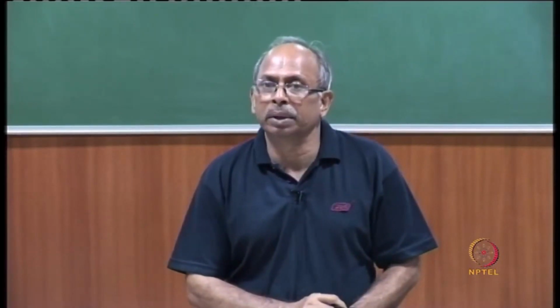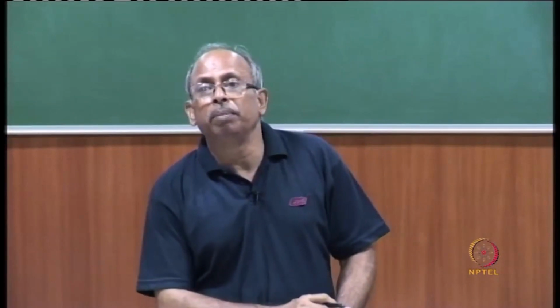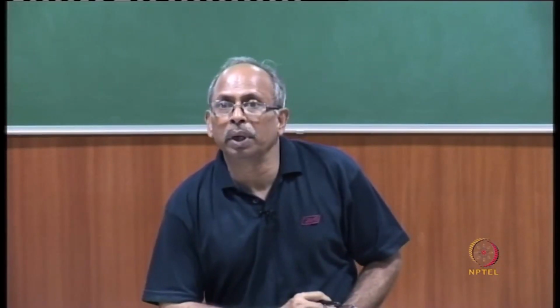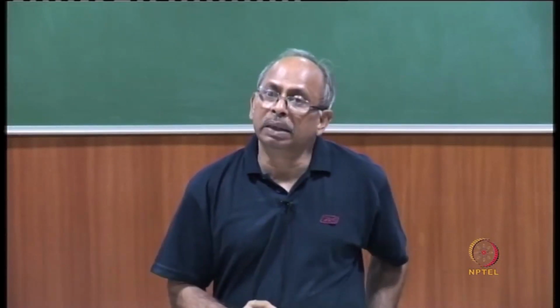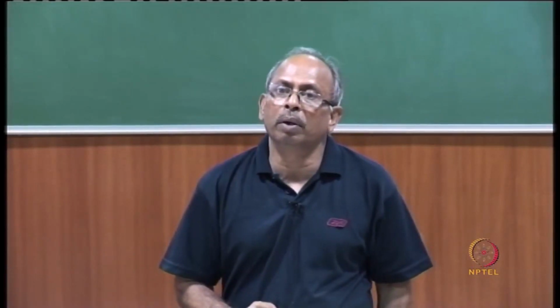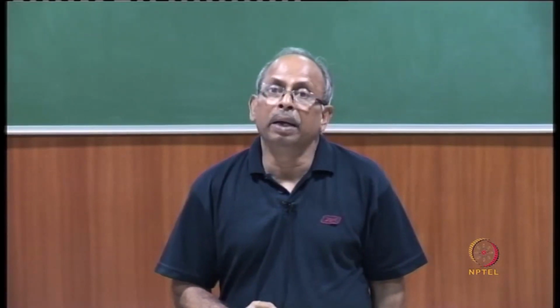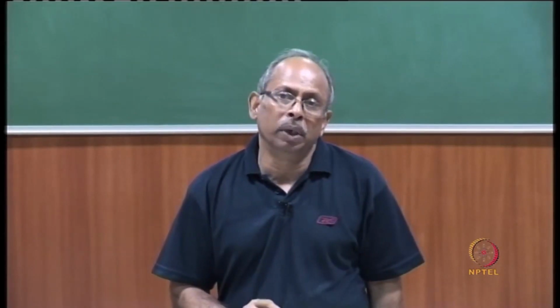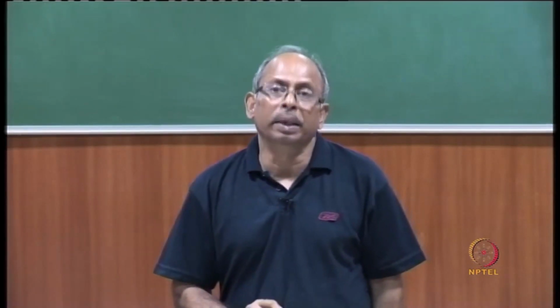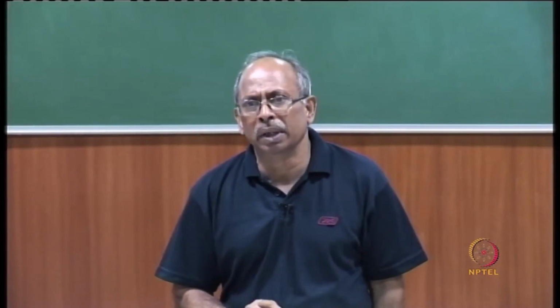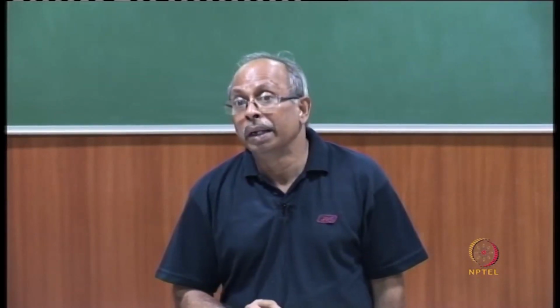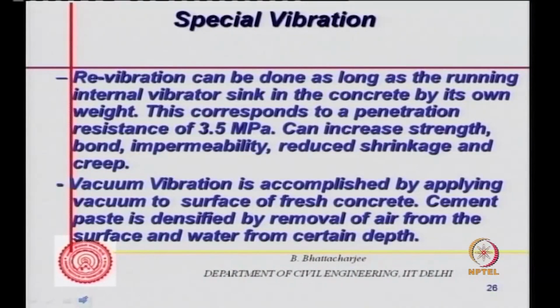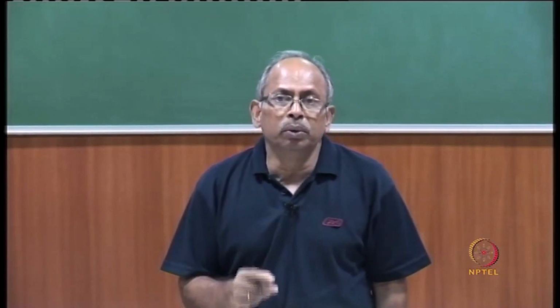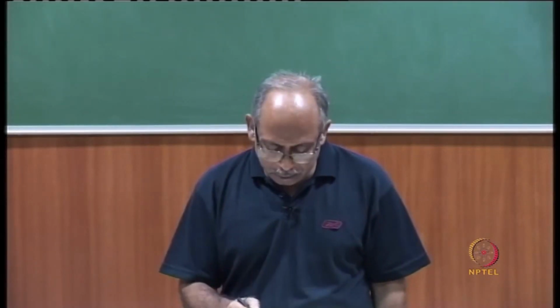It's measured by penetration resistance. Vacuum vibration is accomplished by applying vacuum to the surface of fresh concrete. Cement paste is densified by removal of air from the surface and water from a certain depth. This is applied for vacuum dewatered concrete floorings needing high abrasion resistance, like warehouse flooring or industrial flooring. So this is done where you are likely to have a lot of abrasion. Basically water is removed. This water was used for placing the concrete, but it is removed, so the water cement ratio is low and you get relatively strong concrete.